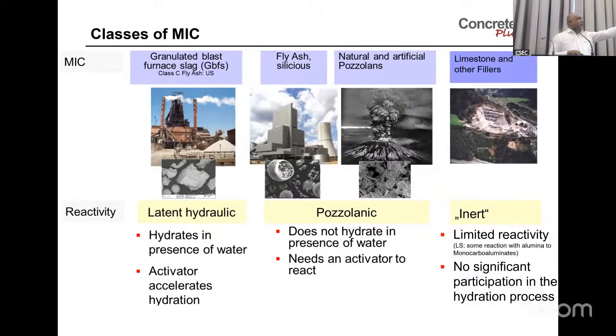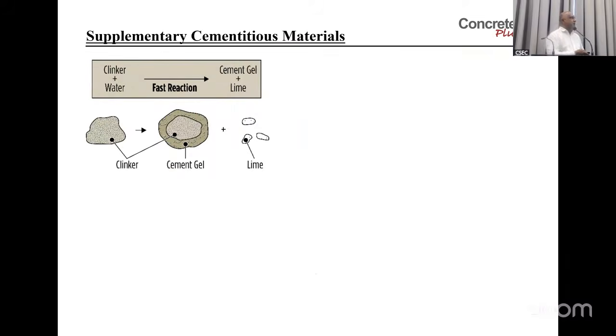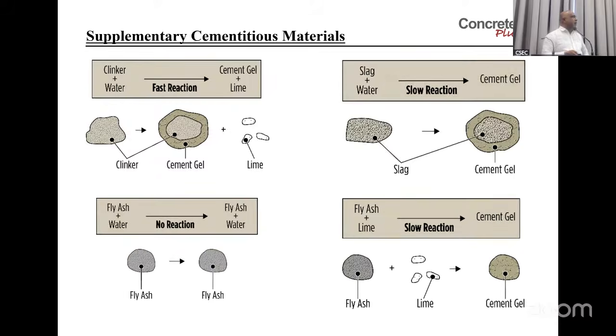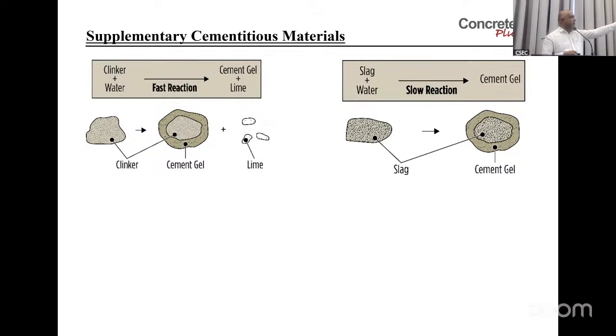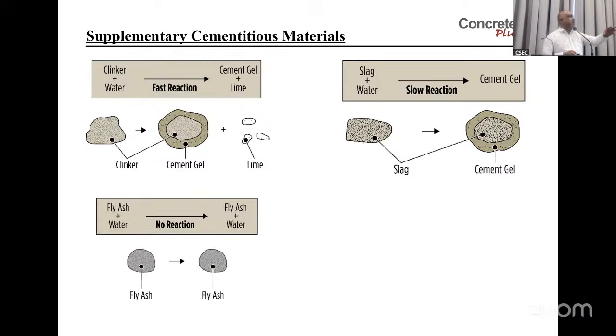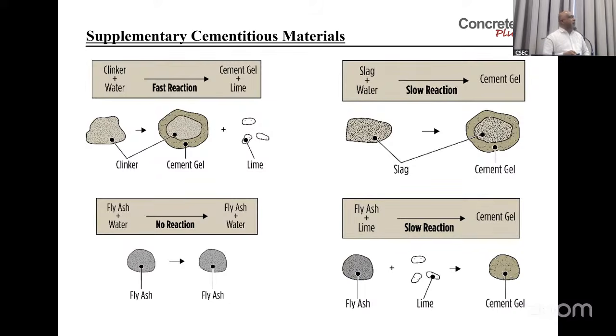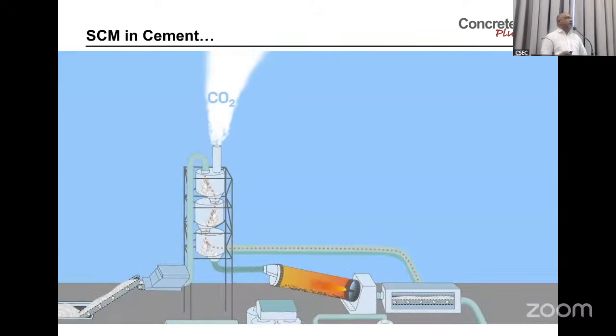Other materials like pozzolanic materials are flaky. So if I just tell you: clinker, there is a fast reaction; slag, a very slow reaction; fly ash, no reaction; and fly ash plus lime, there's a reaction. This is what I told you. Cement has a reaction, slag has a very slow reaction. All the pozzolanic materials react when there is lime in the mix. That's why in the past they always used them with lime, because you need to activate any kind of ash with lime.